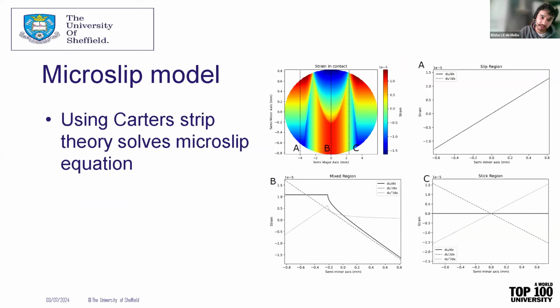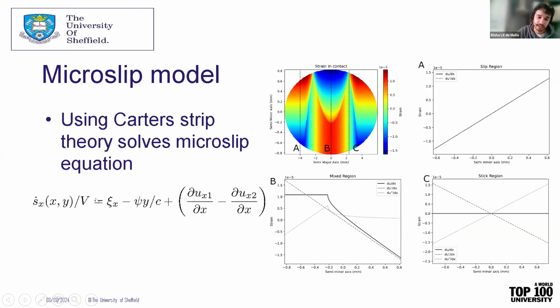And so we're now moving into a microslip regime, and what I did is I used Carter's strip theory to solve the microslip equation. And sorry to throw an equation in here, but basically this looks at a point on the contact patch, and it says that the slip speed is just a function of this term due to geometry, this is a spin speed, so we're neglecting that as we're not assuming spin in the system, and these are strain terms.